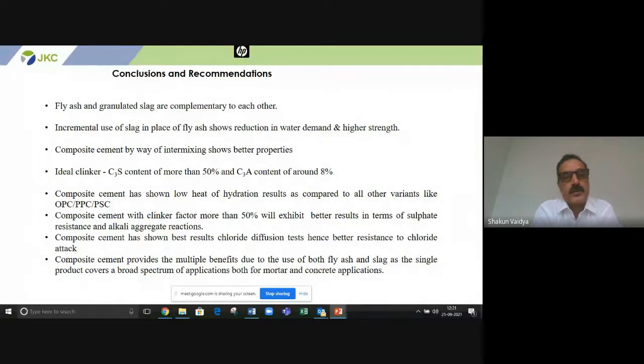Ideal clinker should have a C3S content of 50% and a C3A content of around 8%. Composite cement has shown low heat of hydration. Composite cement with a clinker factor of not more than 50% will exhibit better results in terms of sulfate resistance and alkali aggregate reaction. So we need to ensure that composite cement has a clinker factor of 50%, and we should not go to the permissible limit of 65% clinker.